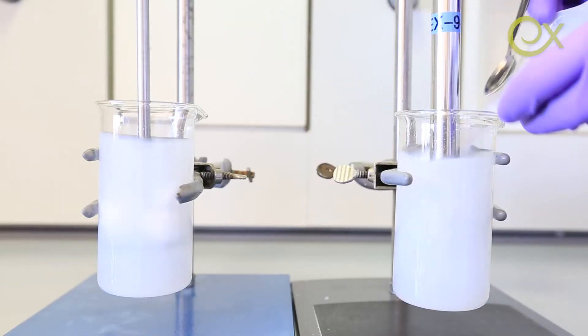When making an emulsion and solving problems, what areas should you be aware of? I think it's the processing — really how you mix the ingredients together — the choice of ingredients, and the concentrations. For example, both xanthan gum and cellulose fibrils should be incorporated in the recommended way. Cellulose fibrils must be added in the water phase, the most polar phase of your formulation. Xanthan gum must be pre-hydrated before use. High-shear mixing allows you to incorporate both correctly and also determines the size of the oil droplets in your emulsion, which affects stability over time.